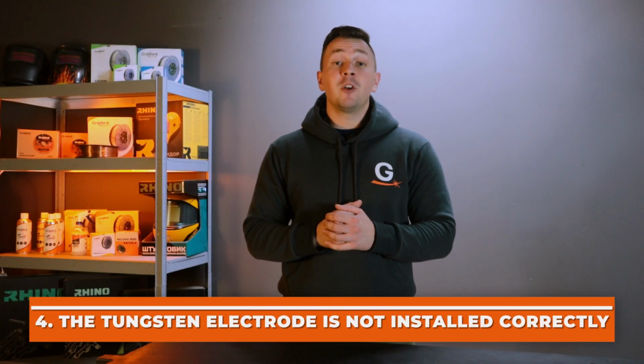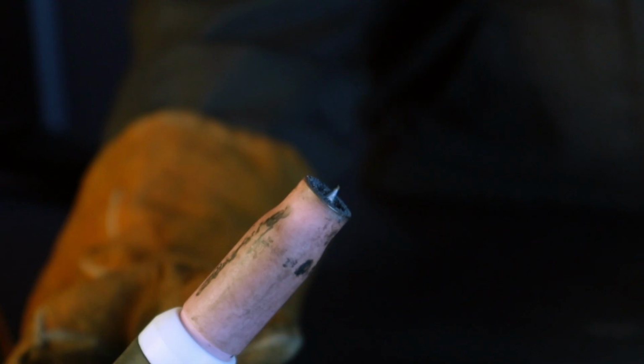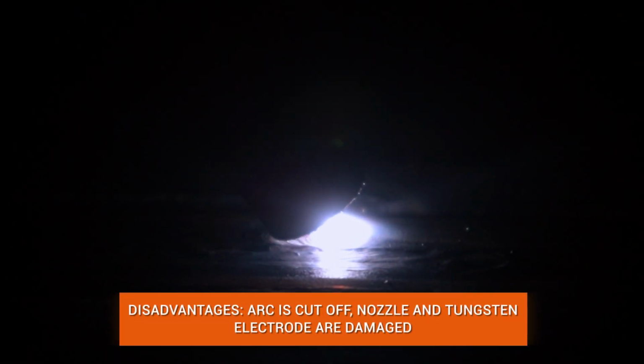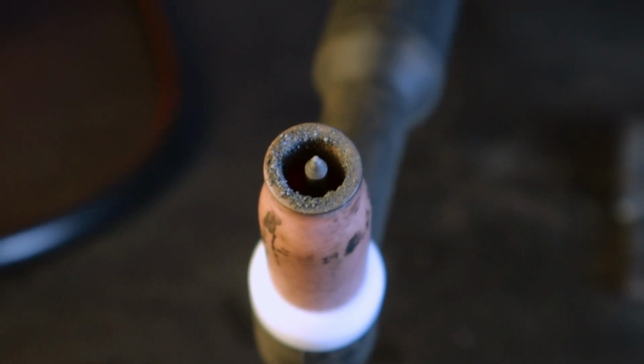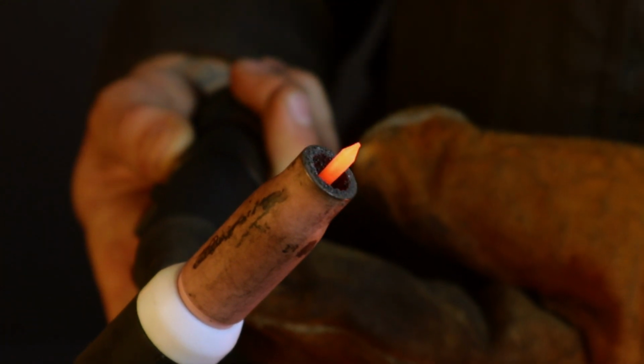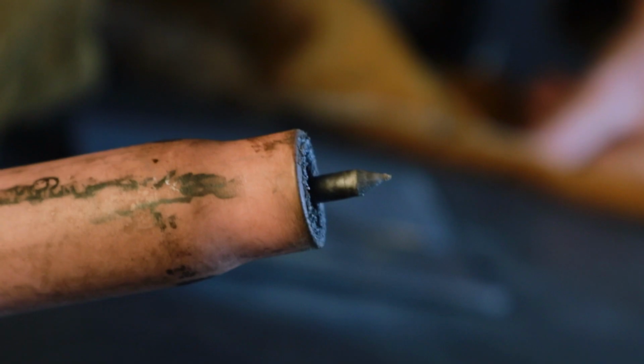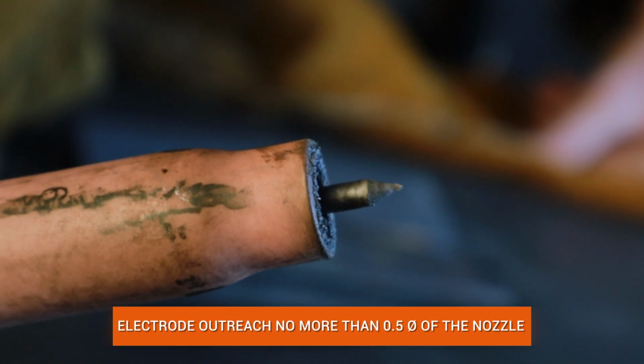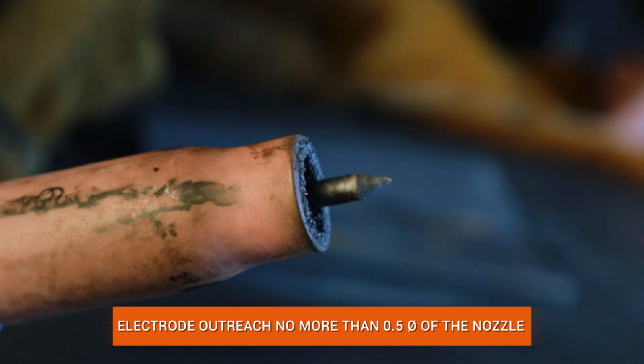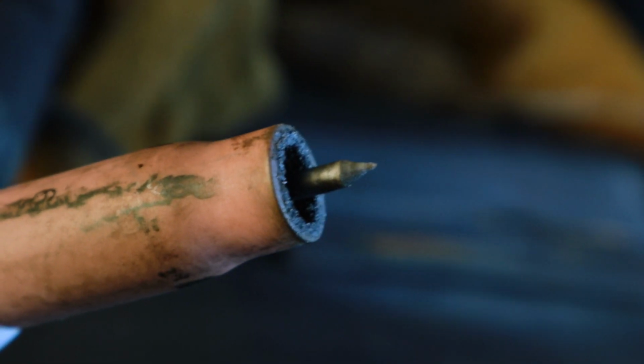Installing the tungsten electrode in the torch incorrectly. Often, novice welders fix the electrode deeper than necessary. This makes it very difficult to create a high-quality welding arc. In this case, the arc is cut off by the nozzle edges. In addition, the nozzle begins to heat up and break down, and the temperature on the tungsten electrode also increases. In such cases, it is important to calculate the size of the electrode overhang from the nozzle. This is usually half the nozzle diameter.